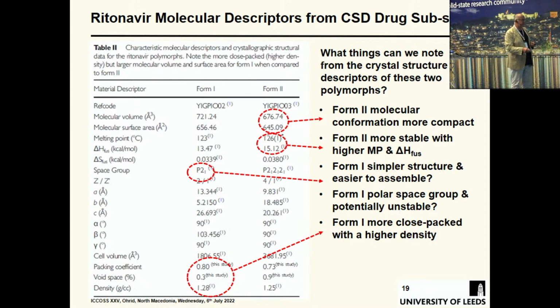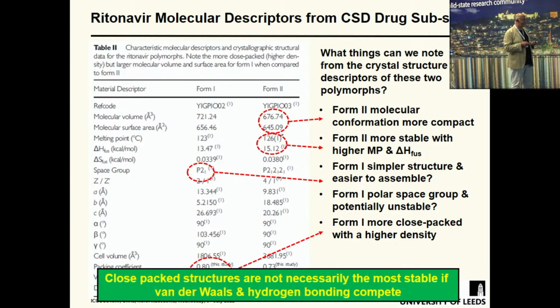But form 1 is more closely packed. See, higher density. This kind of spoils the Kitaigorodskii rules. This is why they're rules and not laws. So here in this case, the packing coefficient is higher, the void space is less, and the density is higher for the metastable phase. That does happen. Close packed structures are not necessarily the most stable. That is the kind of early take-home message. Would they have known at the time? I think they should, really, broadly speaking. And this concept, there are 2 lattices going on.